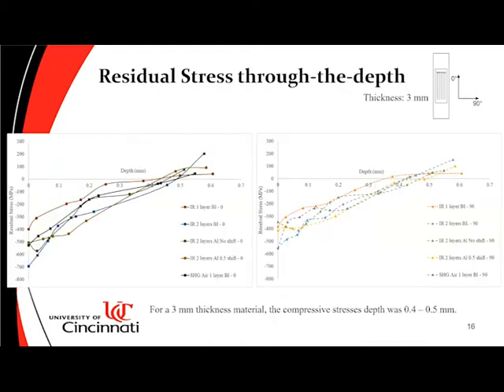So similar to the hardness depth profile, the residual stress profile has highest magnitudes near the surface and also decreases as we go through the depth to about 400 to 500 microns. There's also a difference between the conditions, which highlights the benefits of using different processing conditions compared to the other.